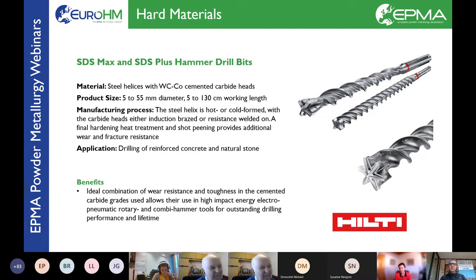And in this case, we are using between 10 and 16 volume percent of the binder, typically cobalt grade, so 6 to 10 weight percent, with a grain size of about 1 to 3 microns, depending on the tool, the type of concrete, the size of the drill bit, the joining technology, and so on. So we have great flexibility within the choice of materials, but it's important also not to forget the manufacturing of the actual drill bit body itself.